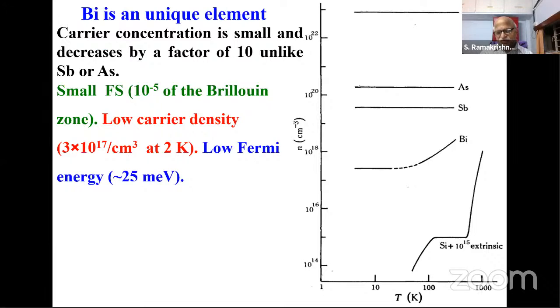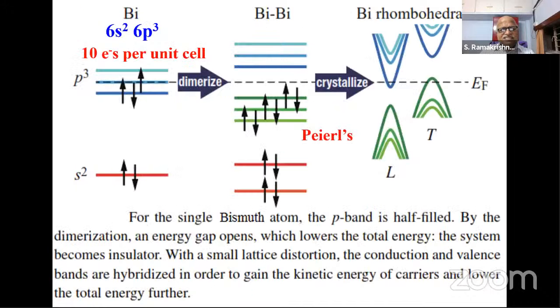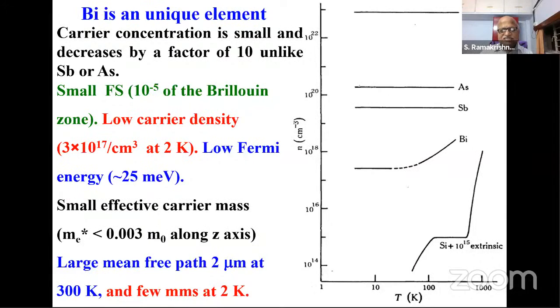This result has been a beautiful result. It's been there for the last 50 years. Still, there is no decent theory which tries to explain why the carrier concentration should go down in bismuth. And as I said, the low carrier density and low Fermi energy, and it has a lower effective mass. So that means because the carrier concentration is small, it has a very large mean free path even at room temperature. It's about 2 micrometers and it can go to a few millimeters at 2 Kelvin.